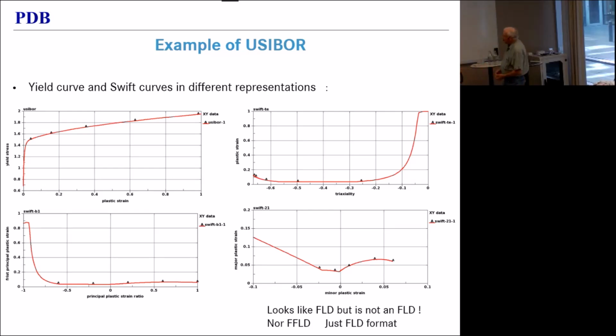You can transform that criterion in function of other quantities. Maybe the most familiar one is here, where we plot the major plastic strain in function of the minor, and then it looks like an FLD. It looks like a forming limit diagram, but it's not, of course. A forming limit diagram gives you the start, the onset of localized necking. And what we have here is the onset of diffuse necking. So you're much lower. About a factor of 2.